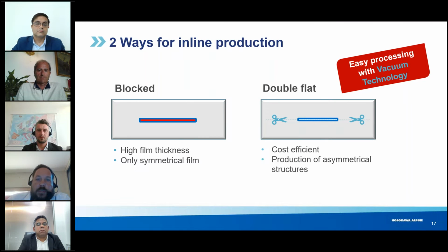Two ways for inline production are possible. The first way, the blocked film production. This leads to a high film thickness, and only symmetrical film could be produced. The second way is the double flat film production. This for sure is more cost efficient, and it's also possible to produce asymmetrical film structures. And for sure, as you may know yourself, the film should be thinner. And this is also an advantage of the double flat, because with a blocked film structure, you will always have a thicker film.